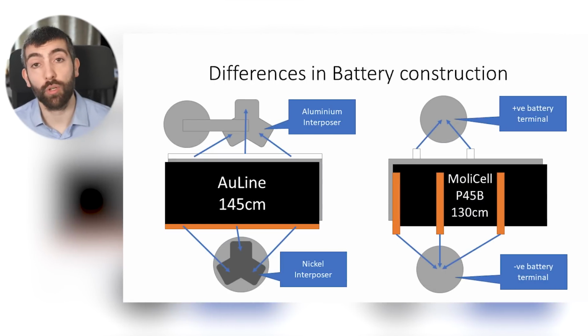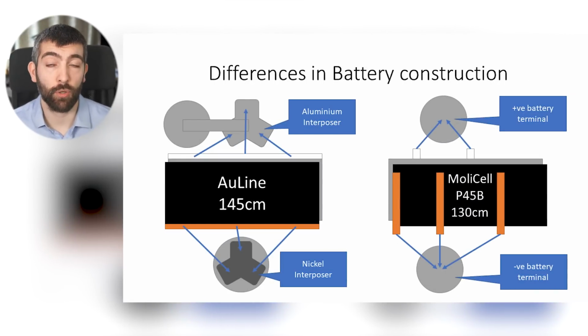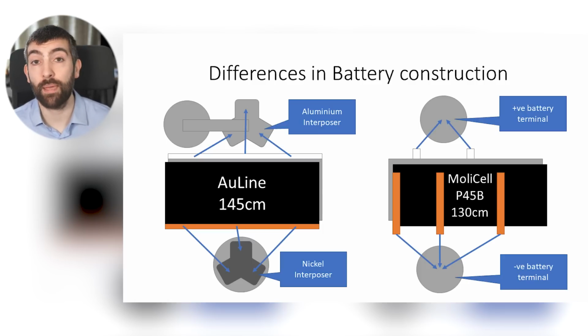resistance. The final thing to talk about is the length of foil in the two cells. The gold line cell has 145 centimeters of foil, whereas the Molicell P45B only has 130 centimeters. Now, you might think this puts the Molicell at a disadvantage, but not so, because with a shorter length of foil, Molicell are able to use slightly thicker foil in their cells compared to the gold line. And that difference in thickness is key to reducing the resistance for electricity to flow through the foil to get to those contacts. This means that Molicell also have to be using a different chemistry.